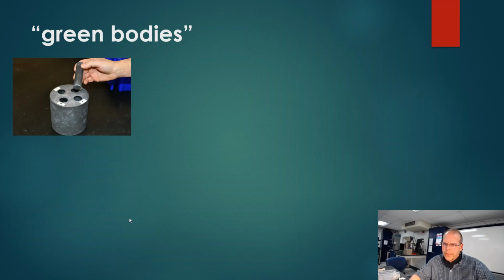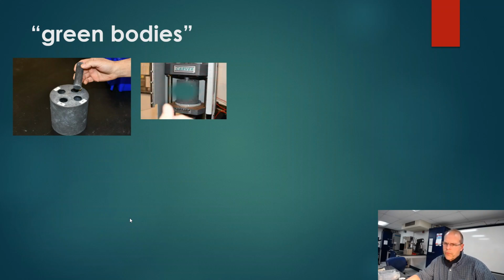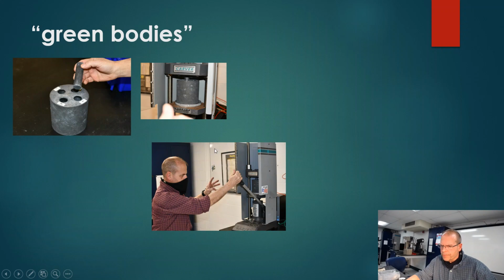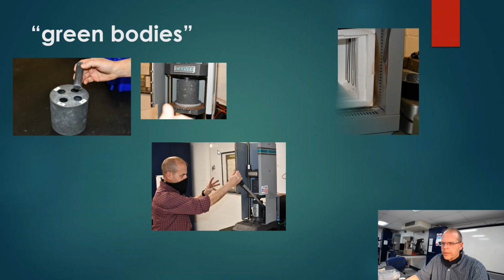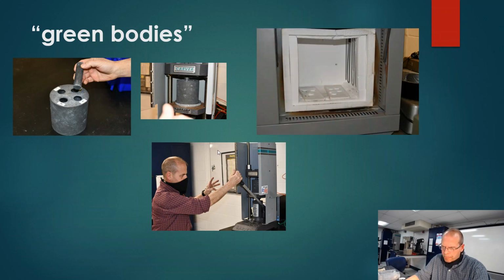We are going to make this through a journey. The journey is going to start by producing these samples, which we like to call green bodies. What green bodies are, basically, we're going to use this graphite mold, and we're going to stick some alumina oxide particles down each of these little shafts, and we're going to compress it, using this hydraulic press. Again, we're going to try to take a snowball and make a very well-packed puck of this aluminum oxide. So when we do this, we'll press it together, and eventually we're going to do something called pre-sintering.